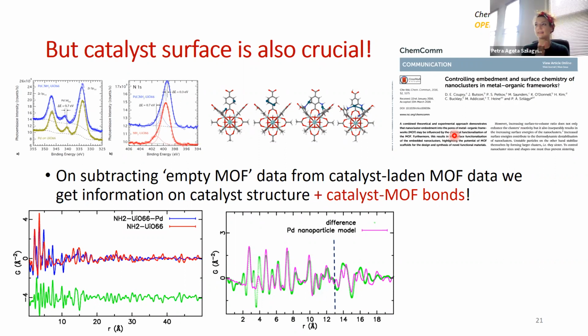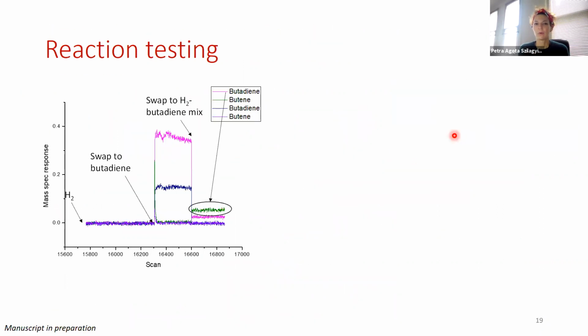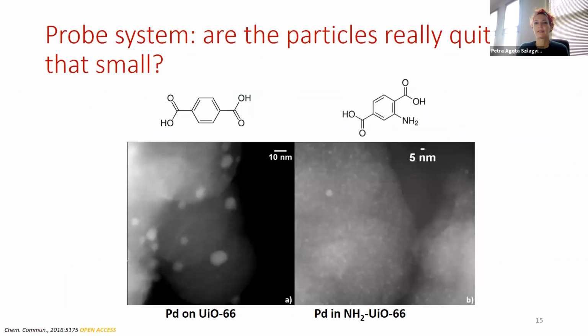So this is the idea that here it's the pore that controls it, that limits it, and then through the functional group you potentially can go lower in size, but the maximum size would come from the pore itself. Now, as I showed here, it doesn't always work. Let me put it like this. In the case of the palladium, but I think for many metals it's the same, we saw that copper likes to fit in everywhere, so it is happy in very small forms as well.